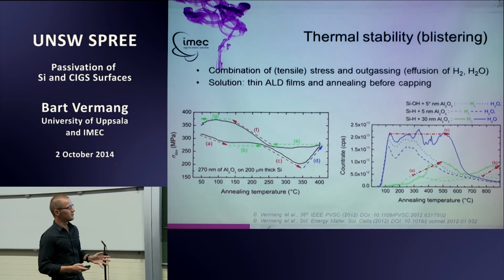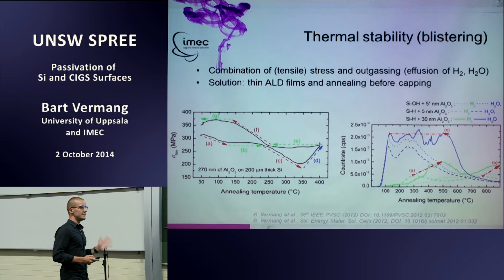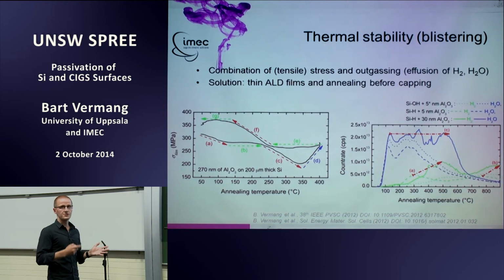So what you could do to prevent blistering is just use thin layers, because then the gas will be able to go through your aluminum oxide layer, and do some annealing before you start to cap it or before you start some high temperature processing. This way you can also get some hydrogen, water out of your layer before it can make blisters. It's logical that you have some H2 and H2O, because in the end, TMA and water were the precursors being used to deposit the ALD aluminum oxide. So it's just some leftovers from the TMA and the water that are still within the aluminum oxide layer.